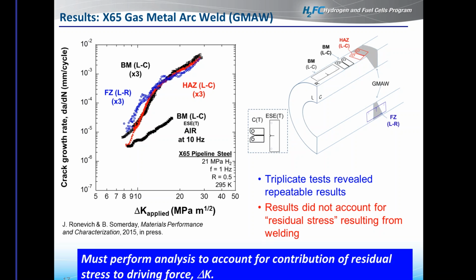So in general, all 3 of these showed similar relationships on a very macro scale. In other words, at lower delta Ks, they became somewhat coincident with the data in air. And then you begin to see that they accelerate quite rapidly and then somewhat follow a similar slope as the data in air, albeit they're about an order of magnitude faster in crack growth rate than they are in air. Now looking more closely at the details, we did run triplicate tests of each condition. We saw good repeatability among triplicate tests.